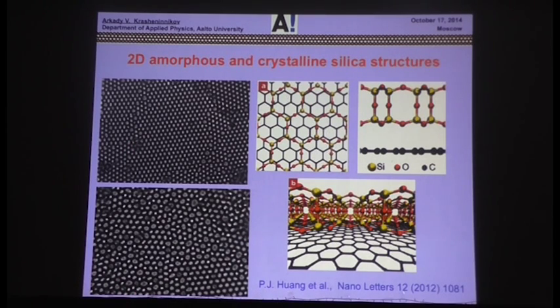And actually, this structure was obtained, in fact, accidentally, serendipitously. Some oxygen and silicon atoms came from the quartz tube used for growing graphene on copper substrate, and this silica bilayer was grown between the copper and graphene layer. Actually, I'll come back later on to this.